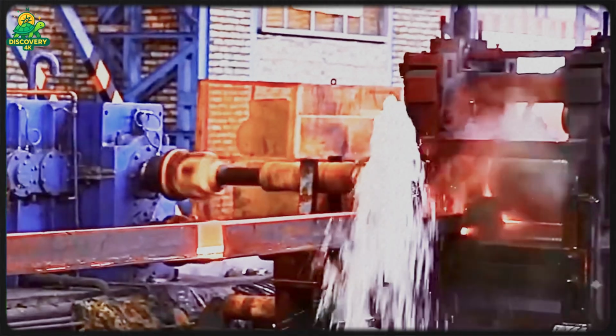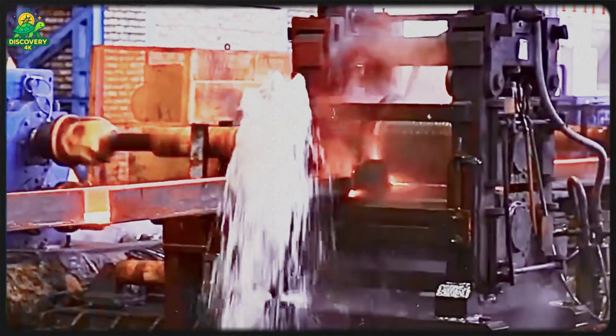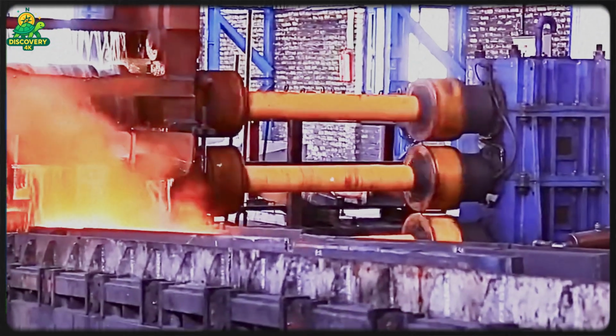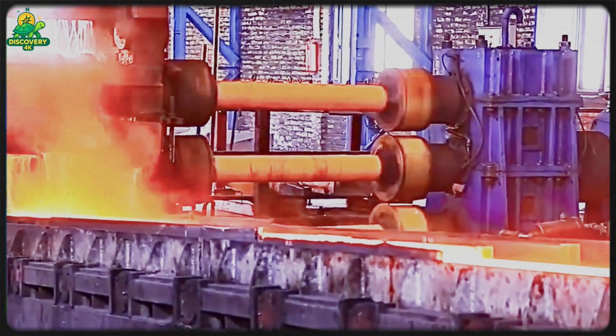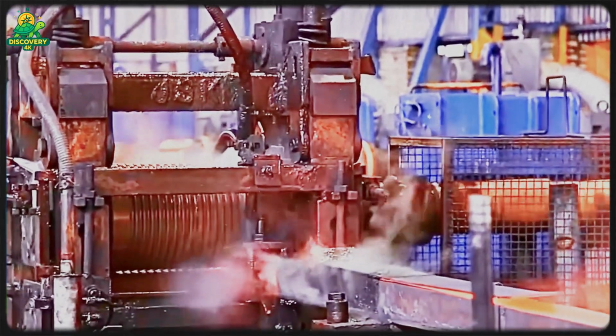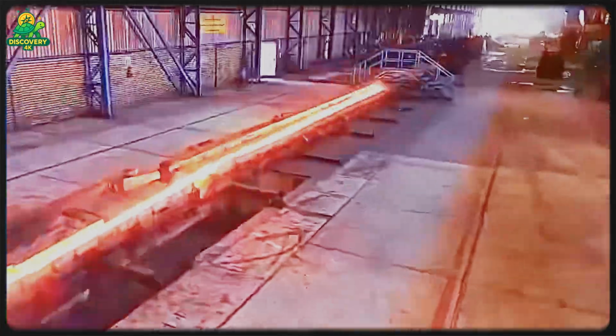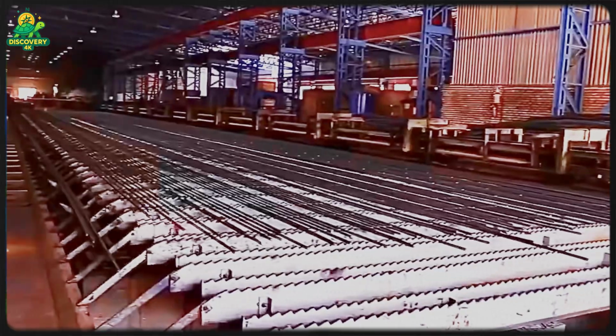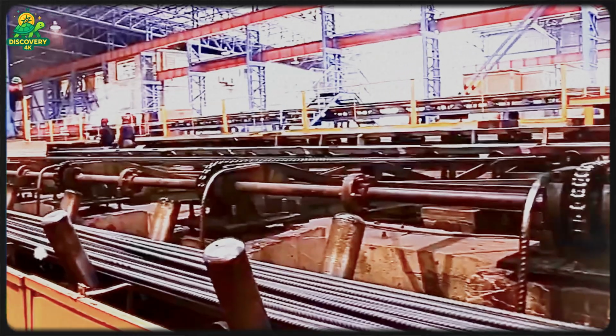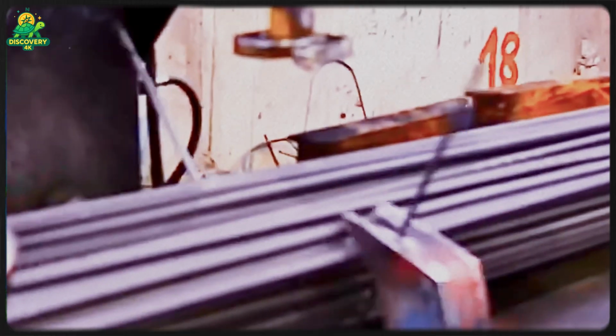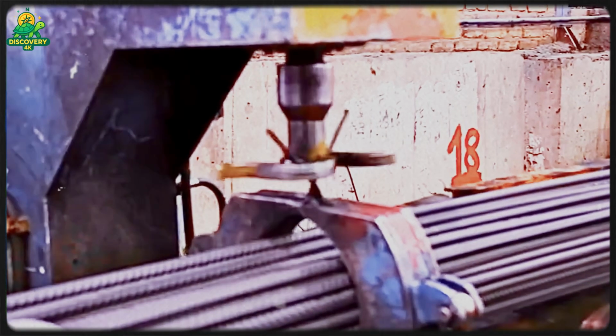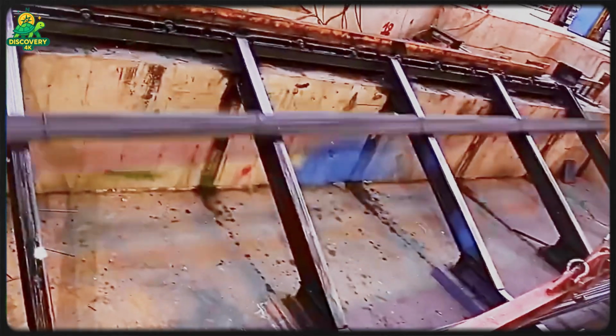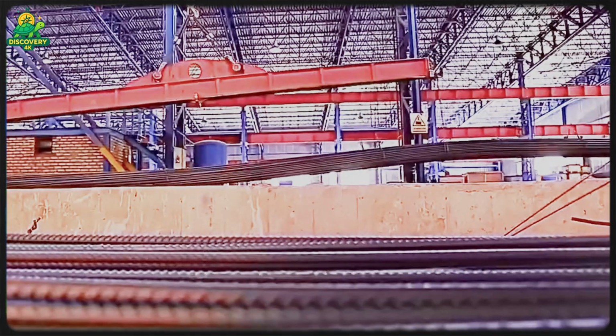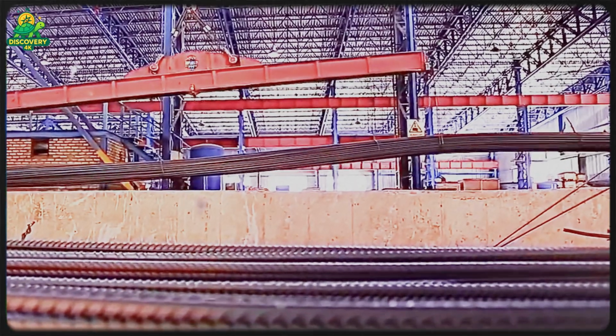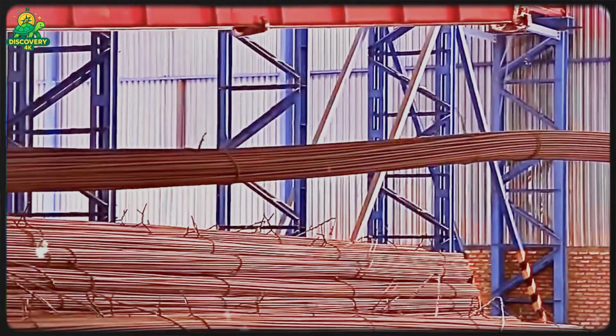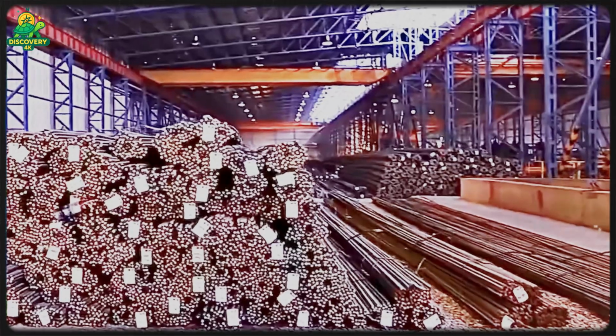But raw molten metal isn't ready to become rebar just yet. It needs refining. The ladle enters the ladle metallurgy furnace, LMF, where engineers fine-tune the chemistry of the steel. By adding small amounts of carbon, manganese, and vanadium, they adjust the strength and ductility. Impurities like sulfur and phosphorus are removed using fluxes. The process is closely monitored by metallurgists who take regular samples to ensure the steel meets strict ASTM standards for rebar. Once the composition is perfect, the steel is ready to solidify. Next up, continuous casting.